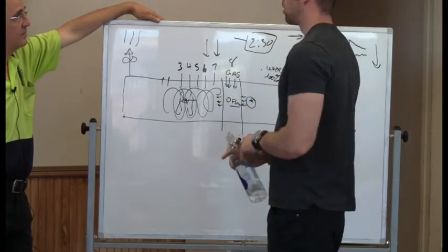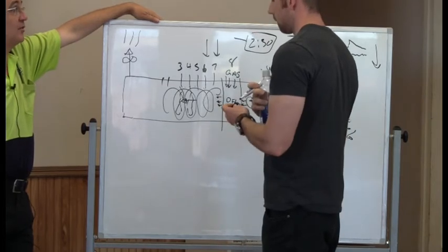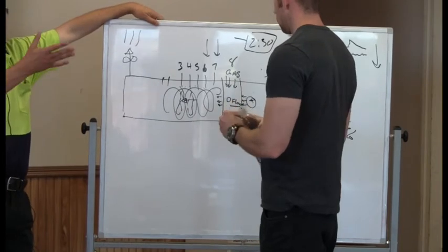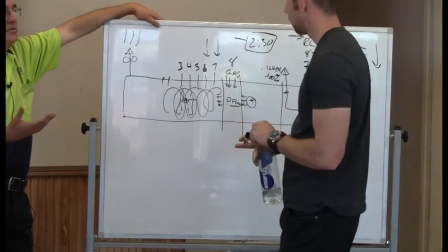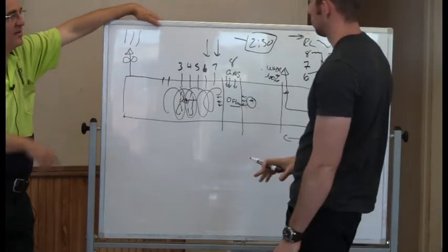And force the air. Yeah. And you would see your temperature actually maintaining or maybe going up, but then when you push, for that period of time, you would actually retrieve that energy in the firing zone.